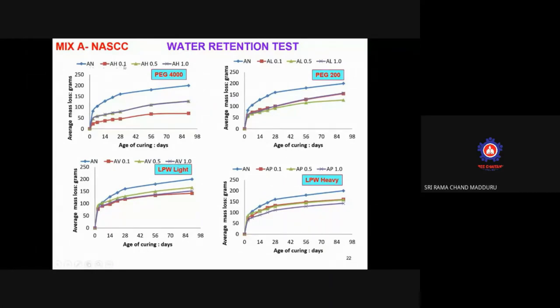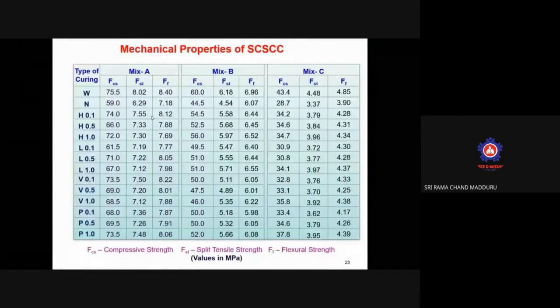Whereas here you can see 0.1 is nothing but the dosage, the percentage of chemical that is added with respect to weight of cement. 0.1%, 0.5% and 1%. And I am showing you typically four types of self-curing chemicals. You can observe that when no curing chemical is added, there is an increase in the mass loss. But when you add these self-curing chemicals, there is a reduction in the mass loss. That means that the moisture loss is reduced. And when the moisture loss is reduced, then obviously there is an improvement in the mechanical properties.